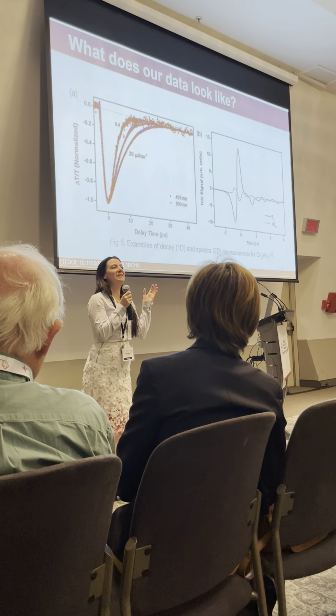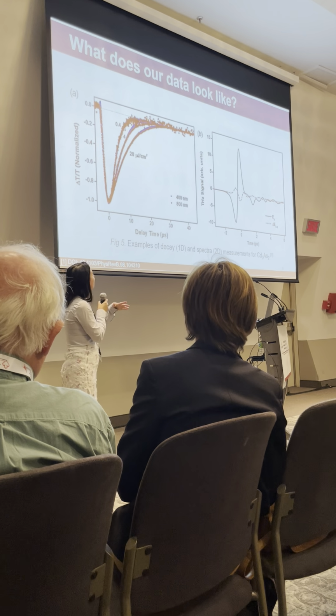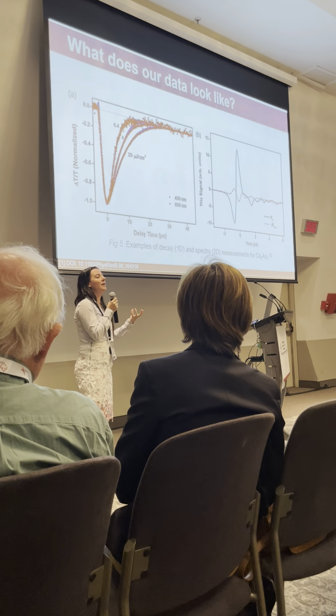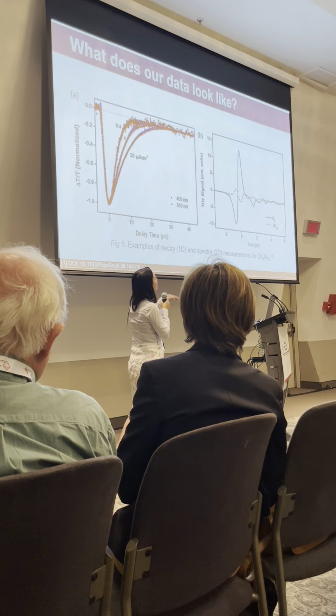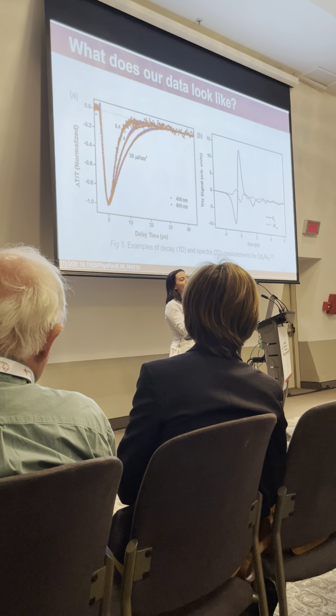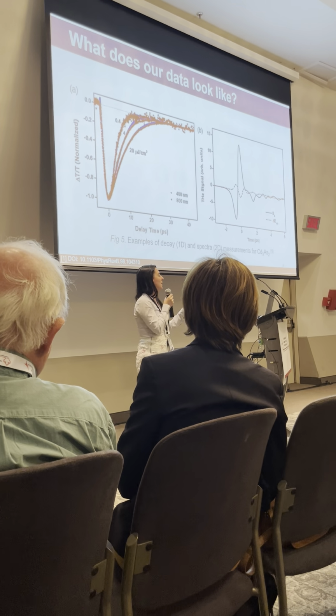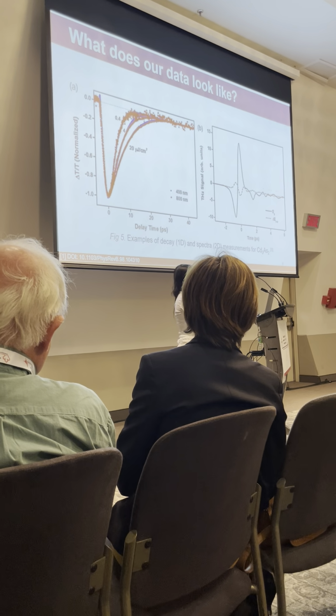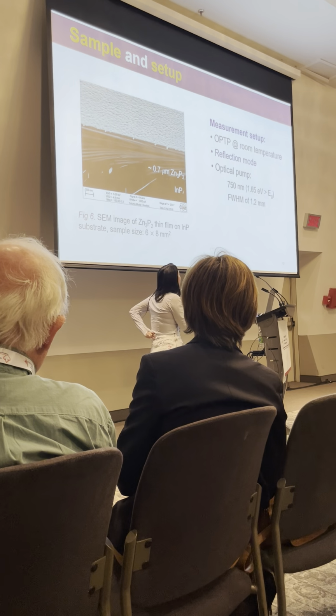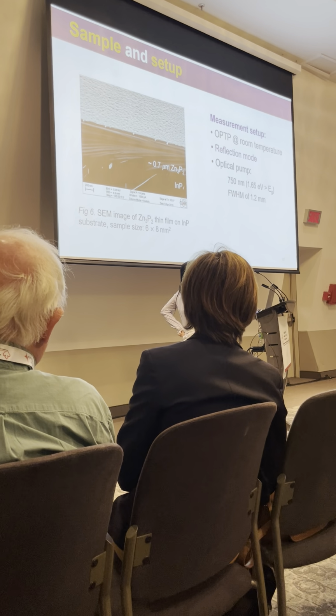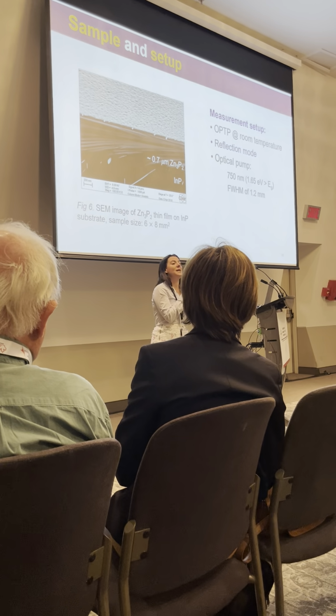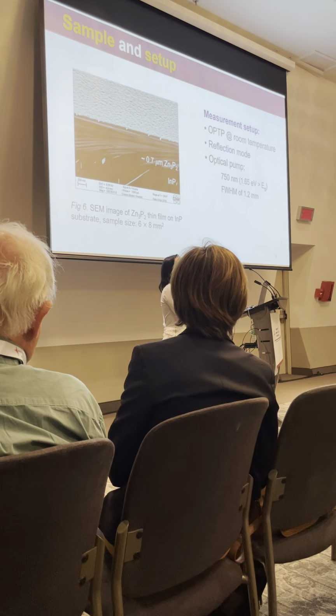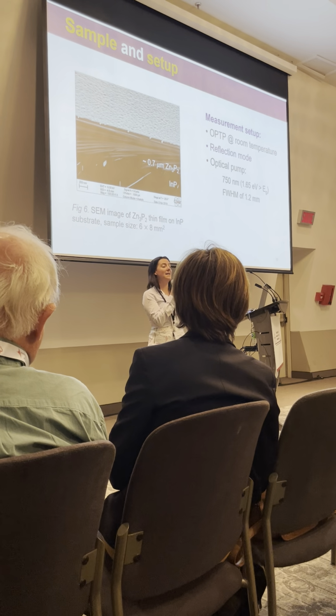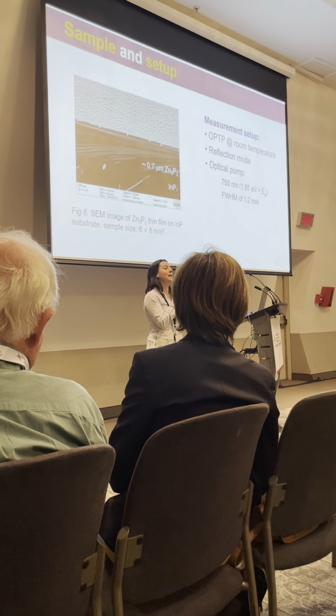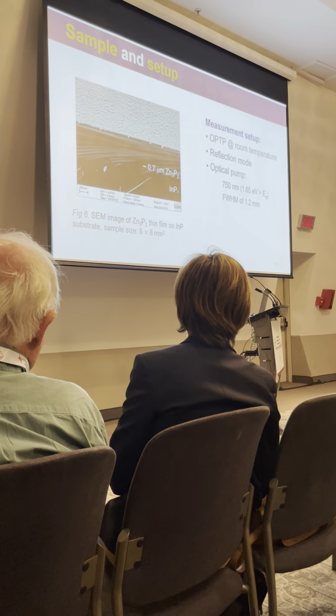So you can look at that change in reflected signal as a function of time after photo-excitation, and that will tell you about the carrier lifetimes of recombination, but also you can look as a function of delay between your terahertz and gate beam, a function of frequency. So we're doing this in reflection, and we're also using an optical pump at about 750 nanometers. This is about 1.65 electron volts. So it's above band gap, so we should be generating electron and hole pairs.